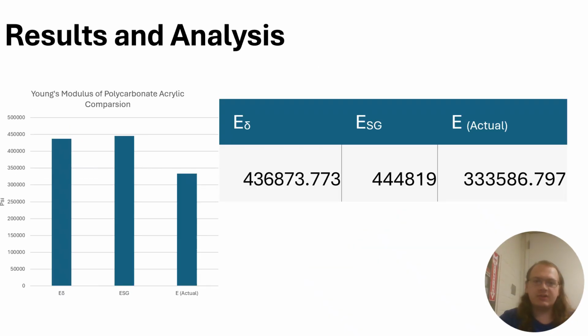The Young's modulus from displacement is 436,873.773, and the Young's modulus from the stress strain graph is 444,819, very similar numbers, while the actual Young's modulus of the sample is 333,586.797, which is somewhat off. However, the gap between all these values is well within the acceptable range.